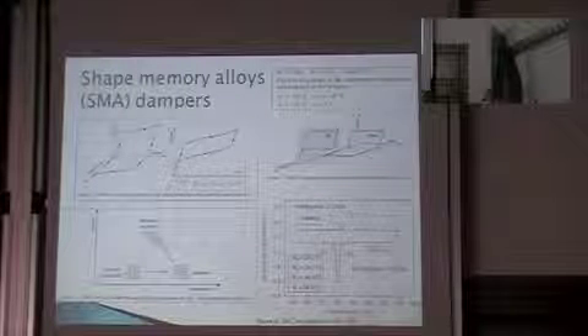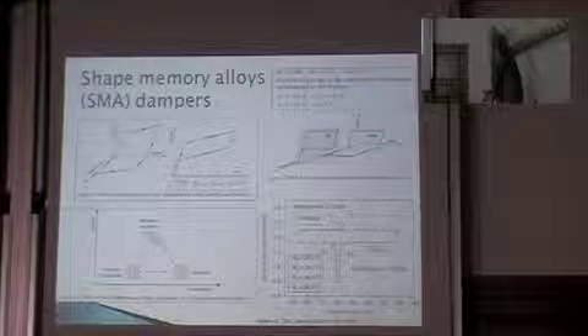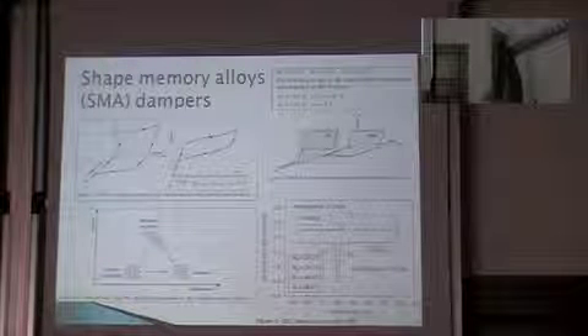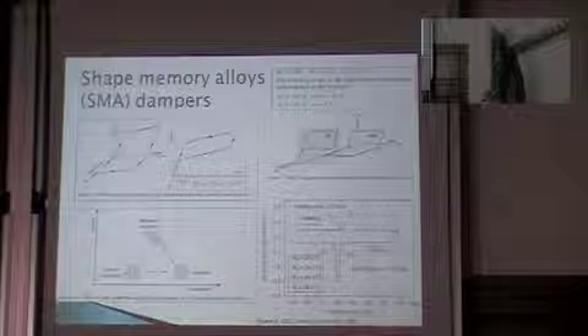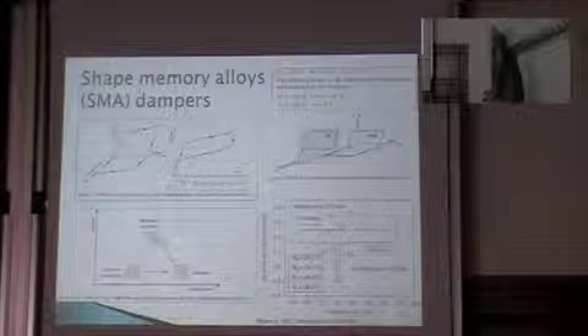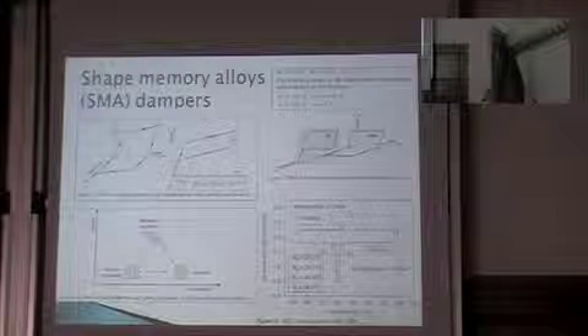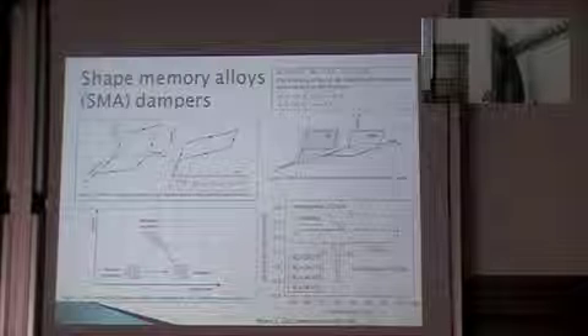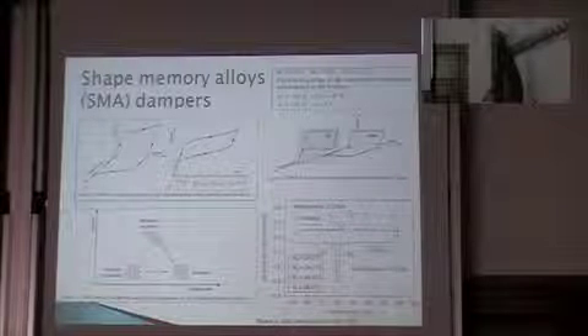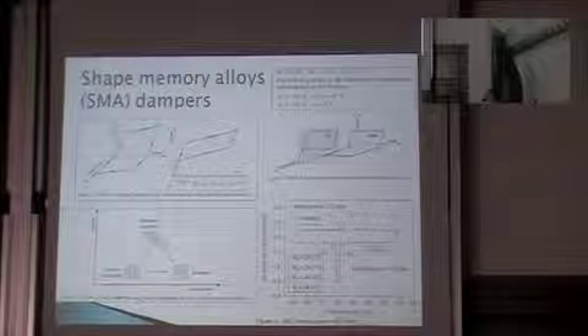So the first thing we need to do is choose the alloy composition. The most utilized alloy is the one based on nickel titanium. It offers some very advantageous properties, such as a very long fatigue life, durability, and corrosion resistance. But on the other side, it has a narrow window, which is at high temperature.